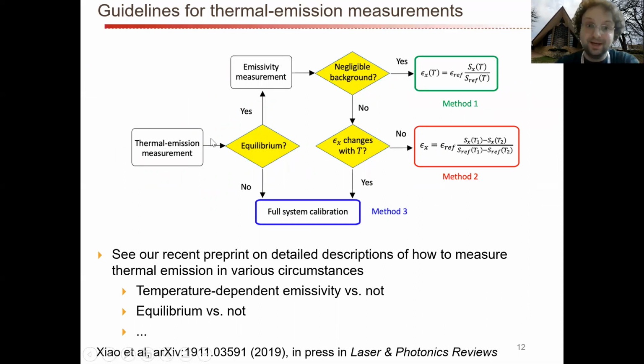So essentially, the flow chart asks you, what kind of thermal emission measurement do you want to do? Is your sample in equilibrium or not? Do you have a background that's negligible or not? That depends on, for example, the temperature of the emitter, the temperature of your background. Is your emissivity changing with temperature? And there's many different ways of how you might go about calibrating your system so that you get really, really good emissivity data from your measurement.